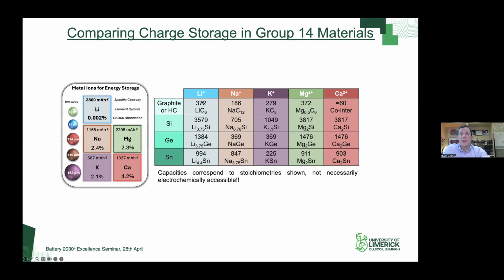Some of the headline ones here, again, that value I'm sure people are very familiar with. That's the theoretical capacity of lithium storage in graphite. Silicon, again, that 3579 is based on this phase down here. You see for germanium, we get up to 1,384. And again, for tin and lithium, we can reach nearly 1,000 milliamp-hours per gram. Okay, so this is kind of the playground where we're working with all of these different group 14 elements and then trying to investigate these various charge carriers and what might be possible in these systems.